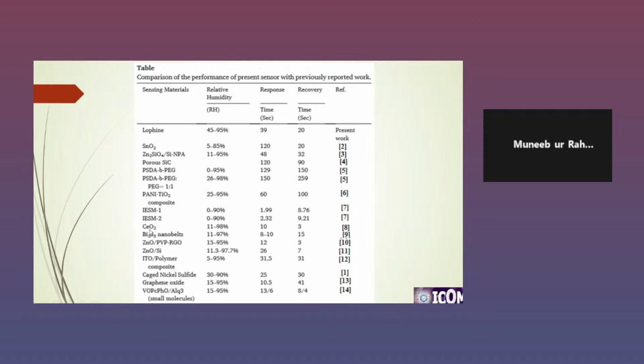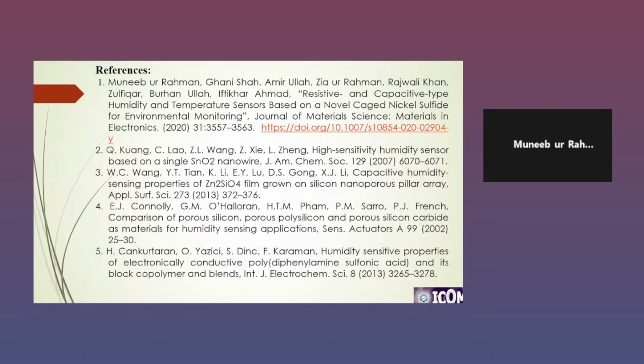For example, CeO2 has a 10-second response time and a 3-second recovery time. So CeO2's response and recovery time is good compared to ours. But mostly we see that our results are quite good compared to the rest of the materials used for humidity sensing. These are the references used in this presentation.